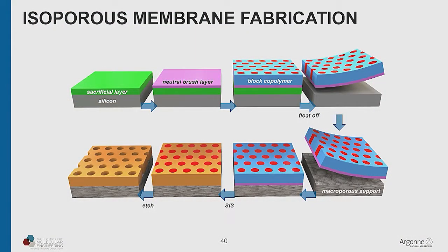And what we're going to do, cool thing about block copolymers is the chemistry, of course, is different in the two blocks. And so you can design it such that the growth only happens in one of those polymer phases and not in the other one. So we can selectively grow in the matrix around the cylinders and then just etch out all the organic. So there's no organic left in the end, and you're left with an isoporous, where all the pores are in principle the same size, inorganic membrane. And you can imagine one could make that out of all kinds of different materials. So that's all a cartoon.